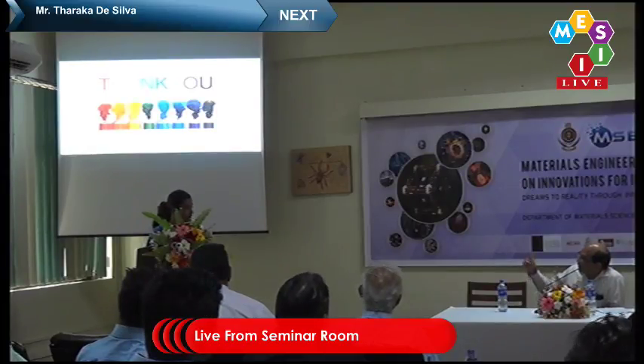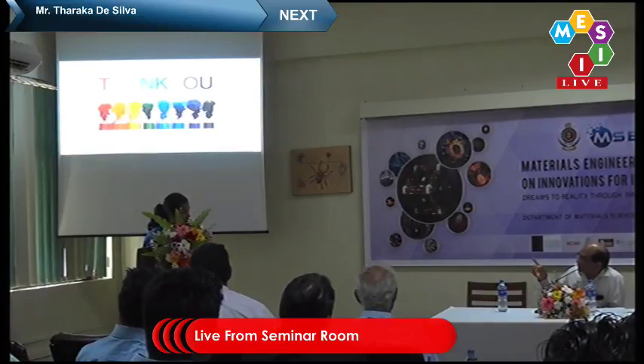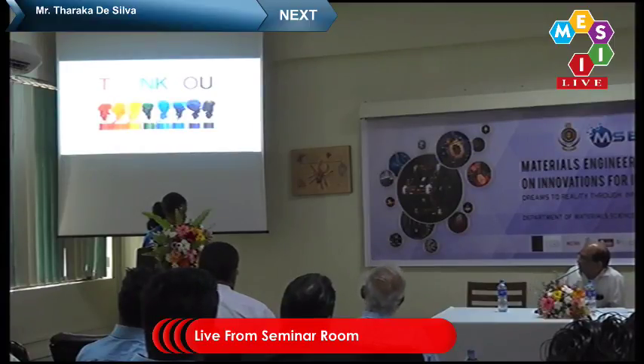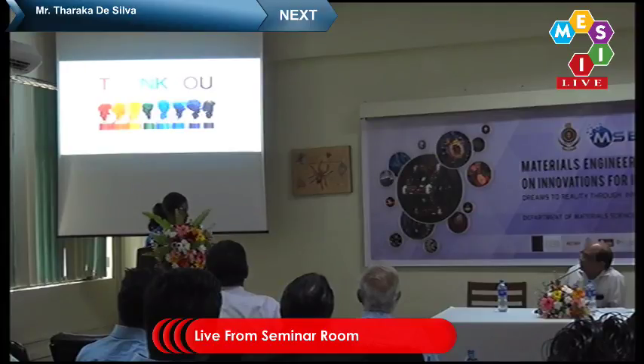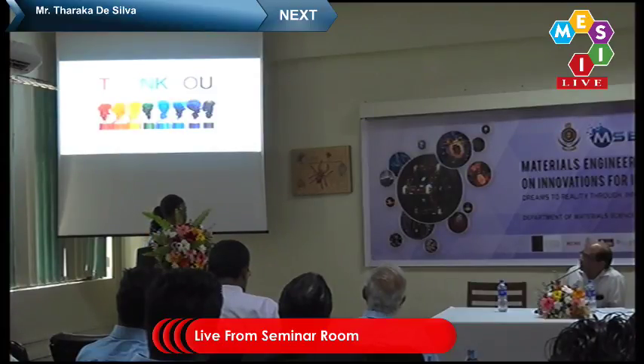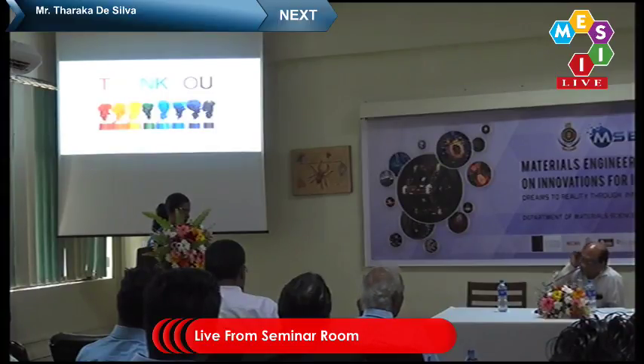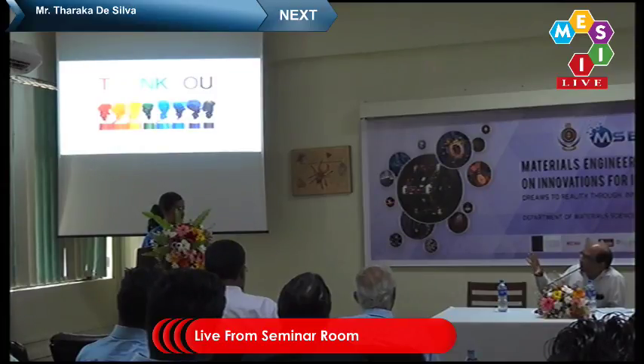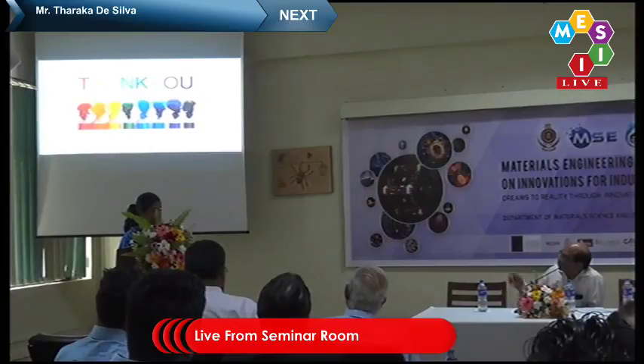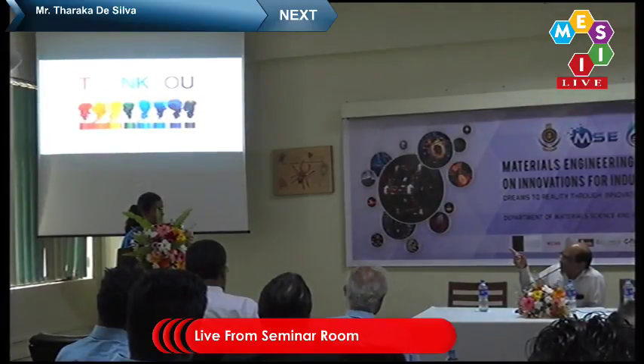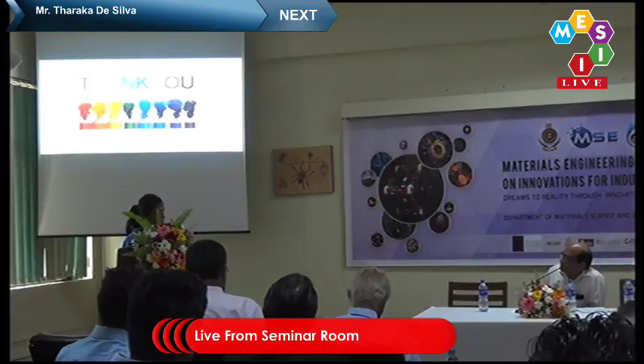Harini, what is the light effect of these dyes? Do you expose them to the light and see whether they degrade with time? Not the values, but how it looks, I mean, are they stable in light? Yes, we did it for 8 hours, 2 days and 8 days. After 8 days, the color did not fade away, even under direct sunlight and direct UV light. Normally when you coat with some other material and expose it to light, it decays quickly. Yes, that is a problem. I think with the cellulose, it makes some complex material with this inside. Yes, because of the metallic salt we used as mordant, I think the light doesn't fade the color dye. Okay.